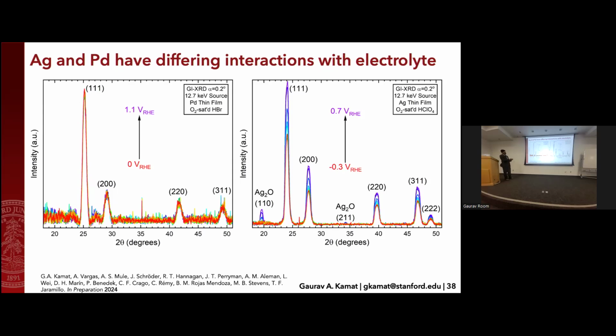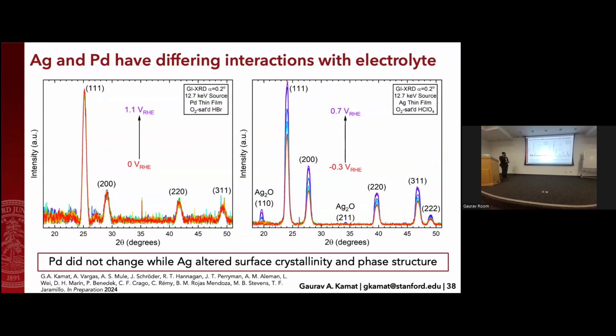And then past certain potentials, you may even be forming a transient kind of silver oxide. Again, this is in the topmost few nanometers, so it's not a bulk silver oxide, it's just at the very top region. And it could be oxygen adsorbates, for example, causing this signal, because silver is one of those materials that's strong binding. It really likes to have oxygen stuck to the surface compared to some other ORR materials. So palladium didn't change, but silver had an altered surface crystallinity and phase structure, as we saw.